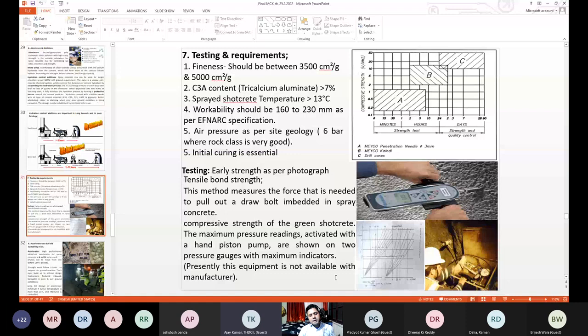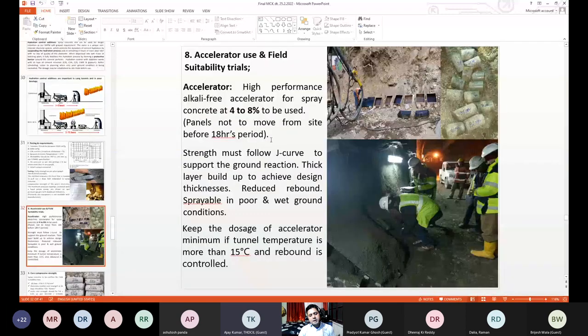Keep the dosage of accelerator minimum if tunnel temperature is more than 15. Presently, at our site we try to keep the accelerator on the higher side, but it is not a good practice. Once the temperature of the site or surrounding atmosphere is okay, then you can keep the temperature of accelerator around 15 to 20 degrees. If it is okay, then you can use the optimum dosage of accelerator. Your optimum dosage will give you the best results.